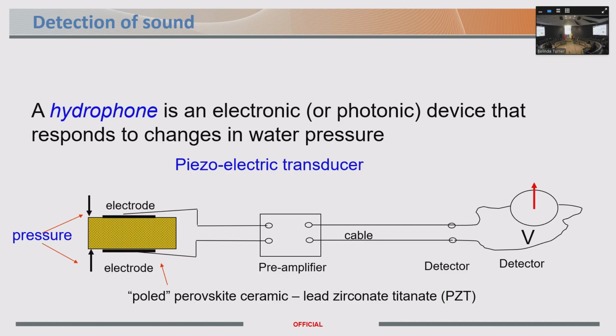And when I say that piezoelectric sensors have dominated sonar since the 1960s, I can actually be more specific than that. It's actually one material, one remarkable material called PZT. And you've probably heard of PZT. It's used in headphones, in microphones, in speakers. It's used in the starters for gas stoves and barbecues. It's a ubiquitous material in industry. But it's also pretty much underpins all of sonar technology. And it has this extraordinary property that it has what's called a morphotropic phase boundary. So it's a binary perovskite ceramic, which is essentially a mixture of lead zirconate and lead titanate.